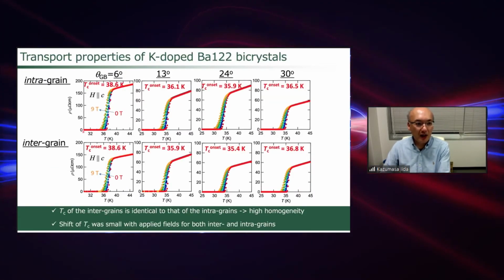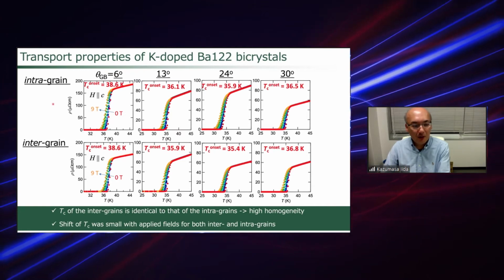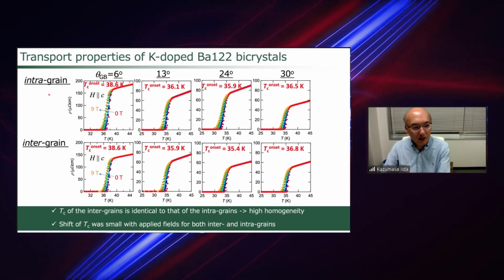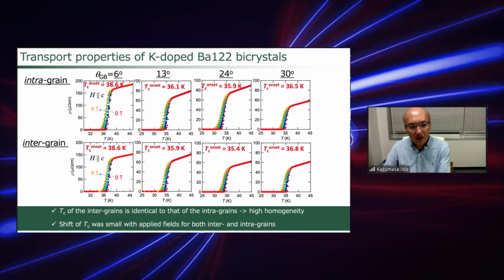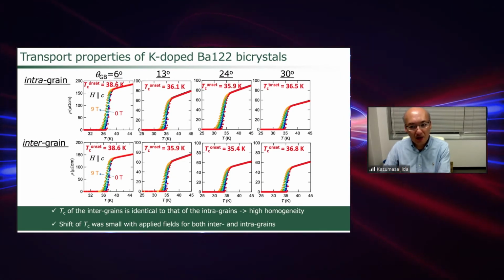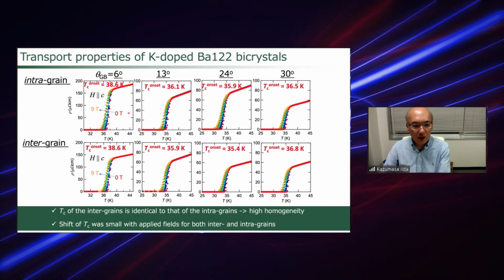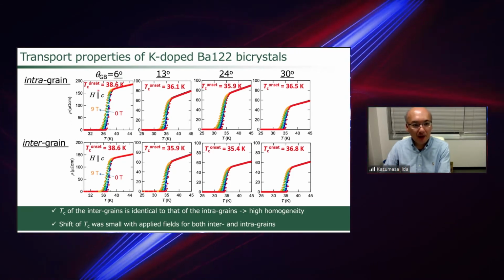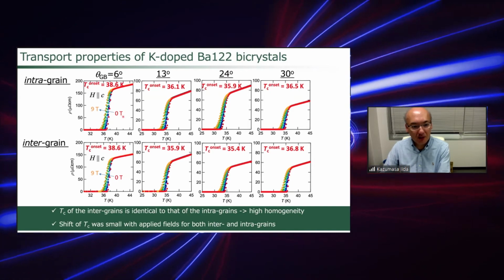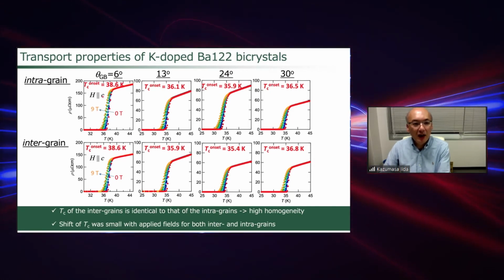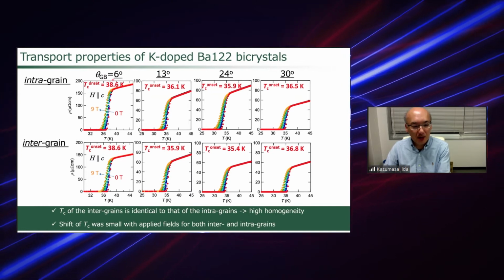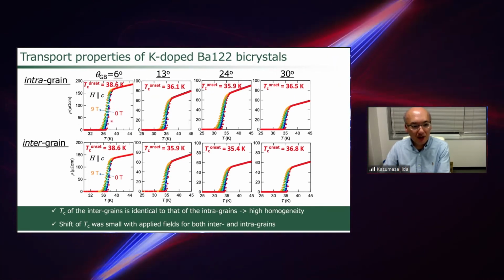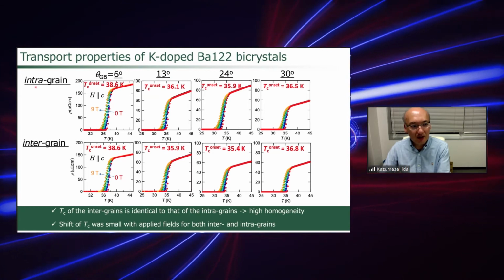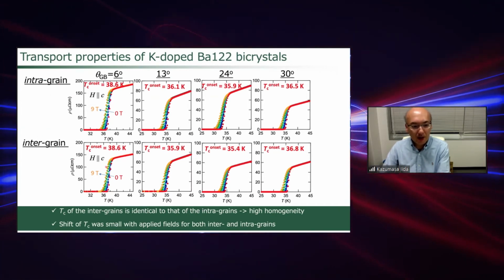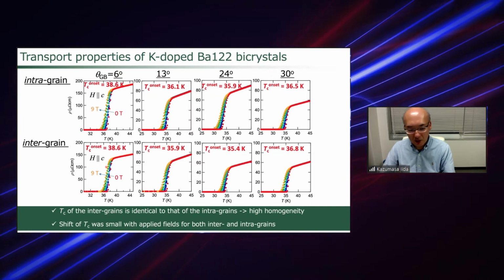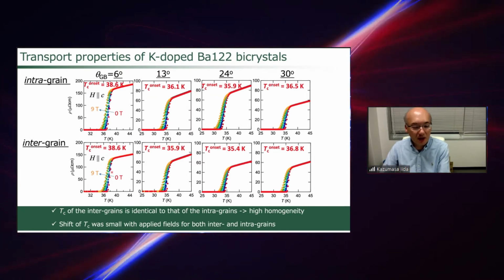And here are the superconducting properties of the intragrain and intergrain bridges, having different grain boundary angles from 6 degrees to 30 degrees. And we also applied a magnetic field parallel to the crystallographic c-axis from 0 Tesla to 9 Tesla. And for the grain boundary angle of 6 degrees, you see that the Tc is almost the same for intragrain and intergrain. That means the potassium is homogeneously distributed within the films.